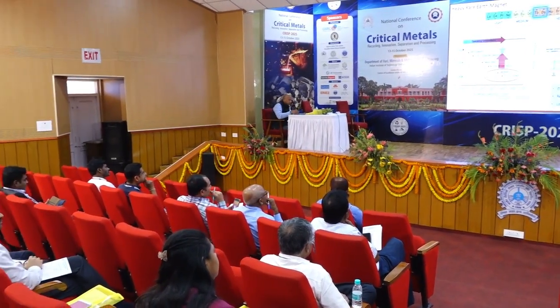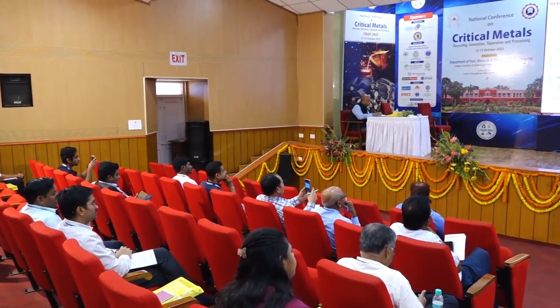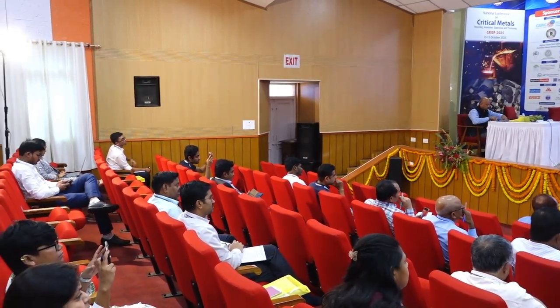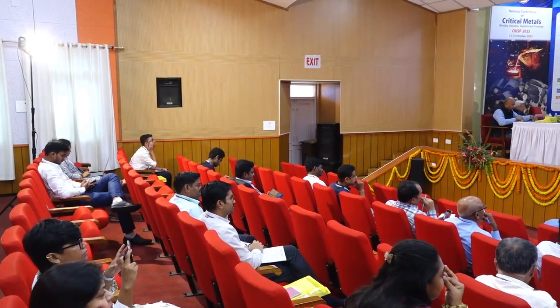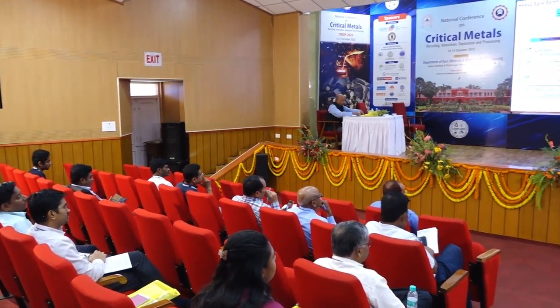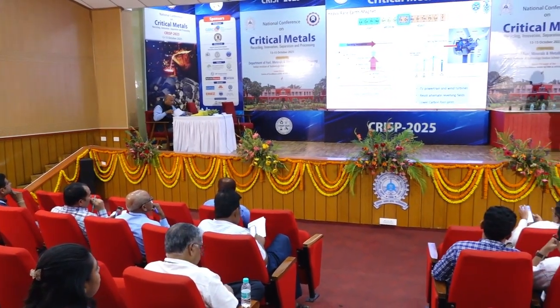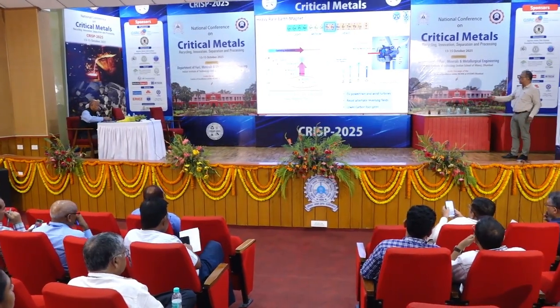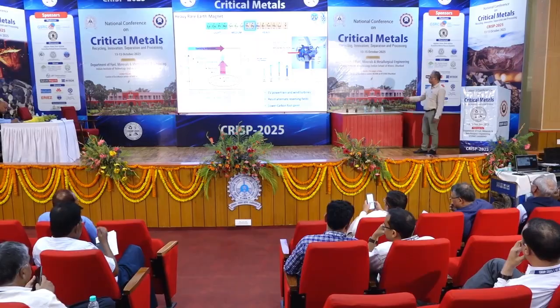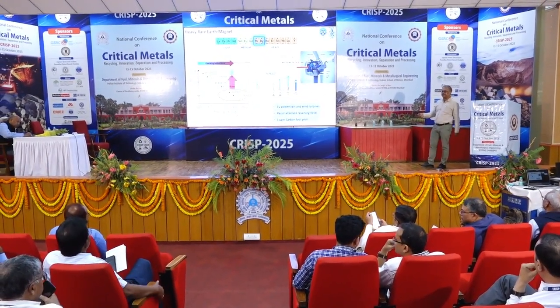So this is another example of how neodymium is replaced by a little bit of dysprosium, along with iron and boron. You can find that the property is quite high in that respect, and that's why it can go at that, as well as the operating temperature, because windmills and other things work 24/7. If it is working 24/7, there is a high chance that the operating temperature can increase, and the addition of dysprosium raises the magnetic property and even reduces demagnetization at high temperature.